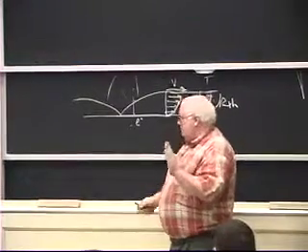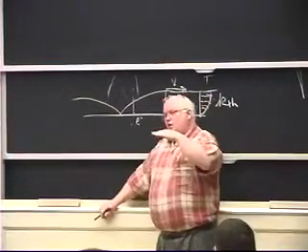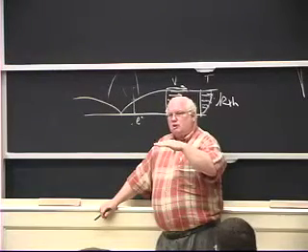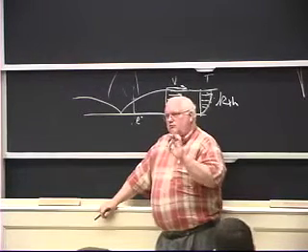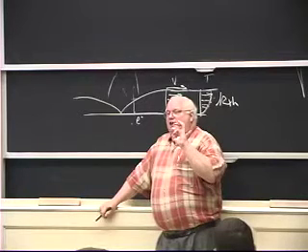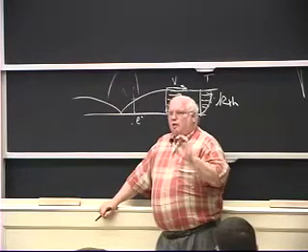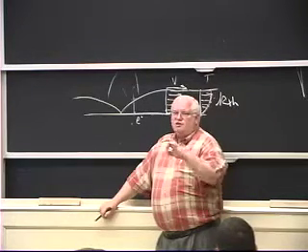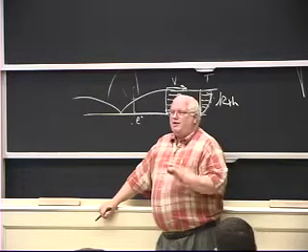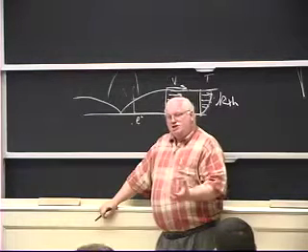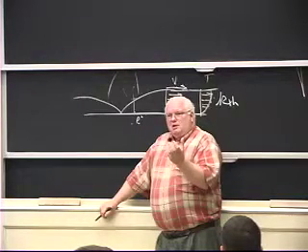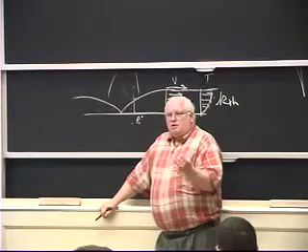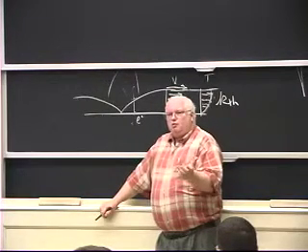Well, it turns out if you're running a pure argon arc on water-cooled copper, that's true. But if I actually were to measure the temperature by measuring the spectral intensity over a liquid steel weld pool, I might find the temperature is anywhere from 6 to 7 or 8,000 degrees Kelvin rather than 10, 11, or 15, because the metal that vaporizes out of there is much more easily ionized, and I only need like 5% or 10% or 15% vapor to produce the electrons.